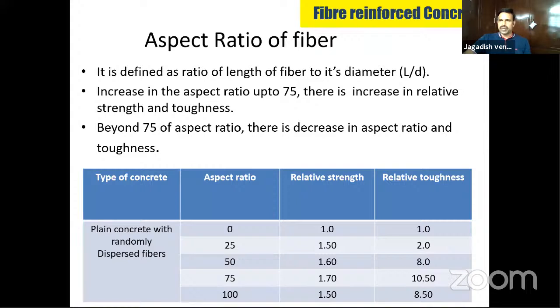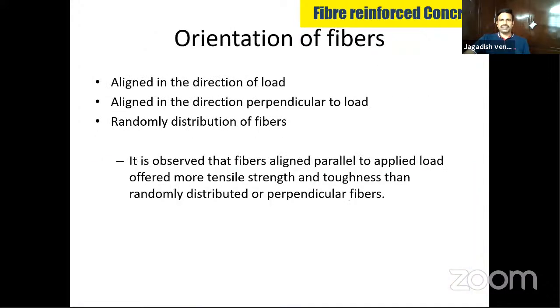Aspect ratio is also a very important parameter. That is the length to diameter ratio of a single fiber. When you look at aspect ratio against relative strength, from 0 up to 75 there is an increase in strength and toughness. But beyond 75, there is a decrease again. So you have to use fibers with an aspect ratio between 0 and 75, the L by D ratio.